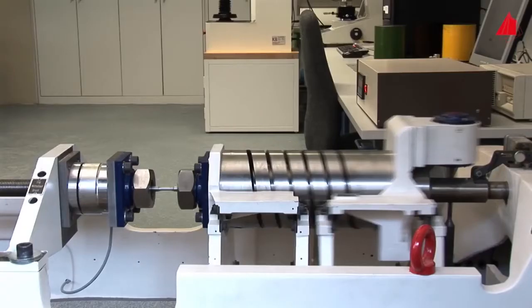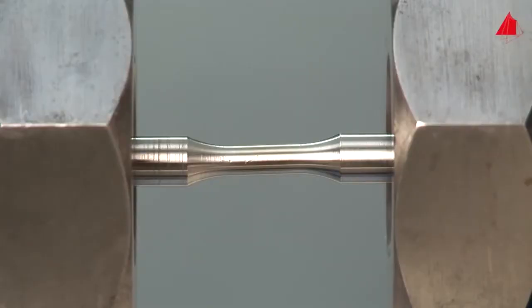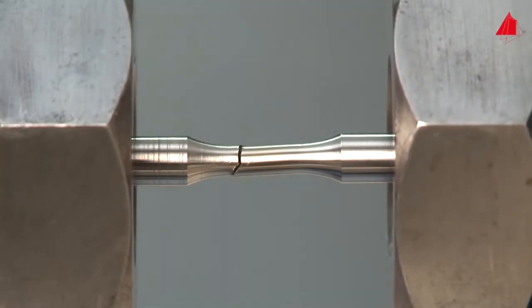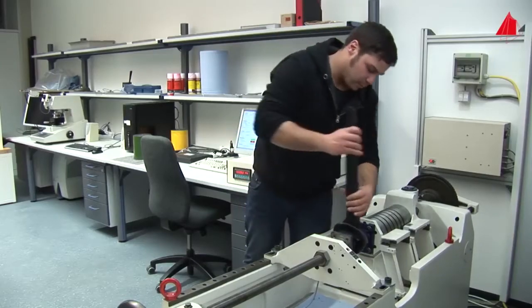Meanwhile, the first specimen has already endured over 300,000 load cycles and still seems to be intact. In reality, however, several cracks have already developed starting from the surface, the so-called fatigue cracks. With each load cycle, they grow a bit further into the specimen. The biggest crack gains the upper hand, grows the fastest and finally leads to fracture after 381,000 load cycles. The first test is finished.